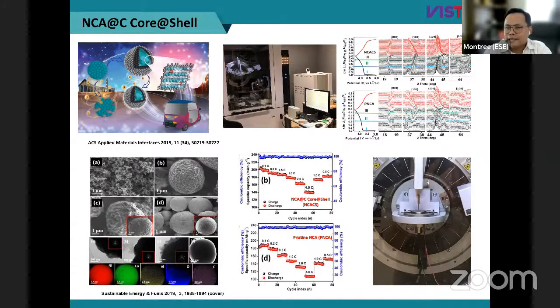We start from NCA and we look at the issues and drawbacks of NCA. In this case, for example, we do encapsulation. We know the issue of NCA is fragile, easily collapses. The safety is a big issue. And for example, in this case, we do encapsulation with our mechanofusion. Without using any chemical, we can enhance 10 or 20% overall performance, like capacity, energy, and longer life, and so on. And also, we improve the safety in this case, and we do research in really fundamental.